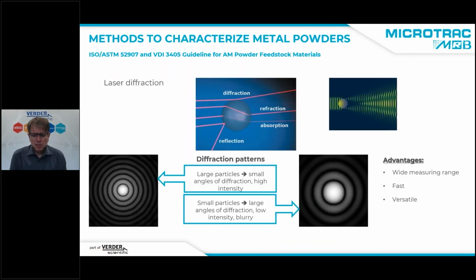The second method that I want to mention today is the laser diffraction. What happens here is we shine laser light onto our particles. When the wave of the light interacts with the particle, we have diffraction, refraction, absorption, and reflection. And this diffraction for the relatively big metal particles causes a diffraction pattern, and this is what we measure. So we measure the light intensity and the direction of the scattered light. And from this, the instrument calculates the size distribution of all particles, because the big particles scatter the light into forward direction and the smaller particles scatter the light sideways.